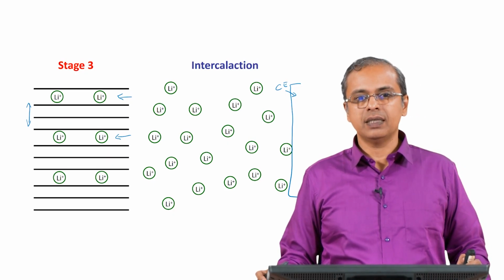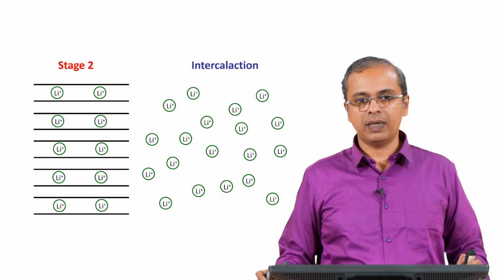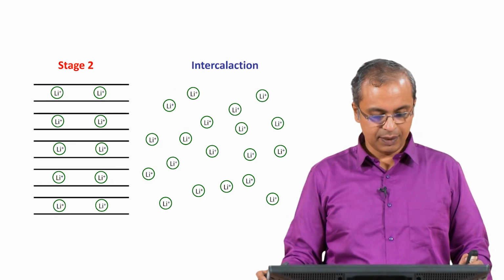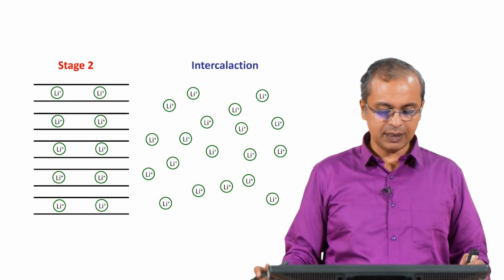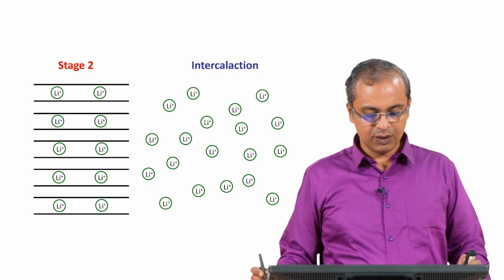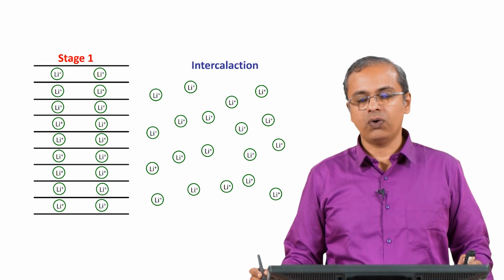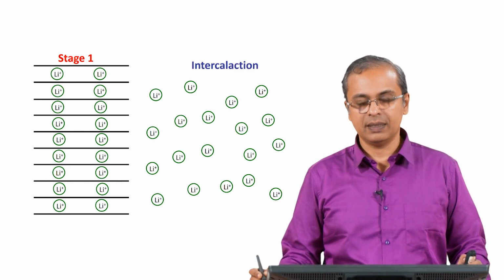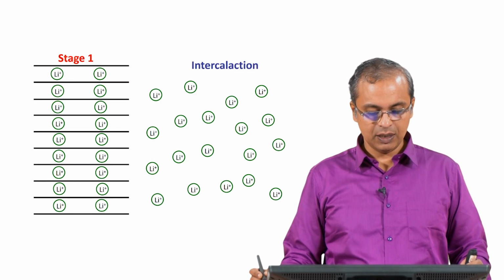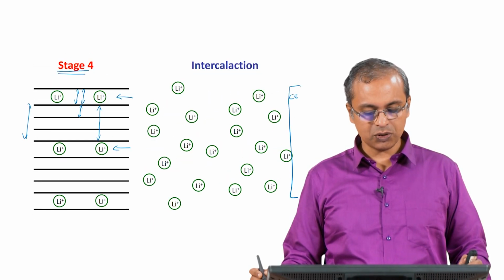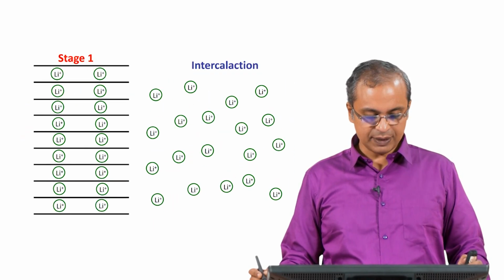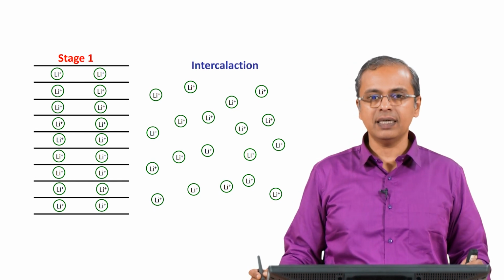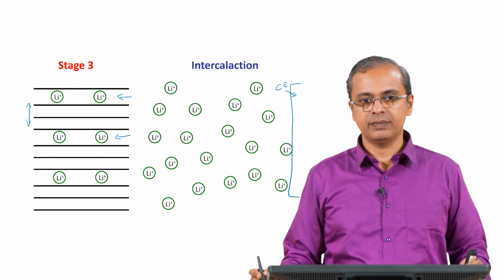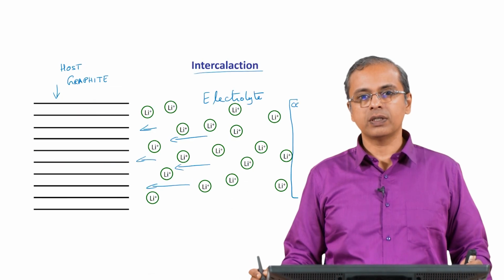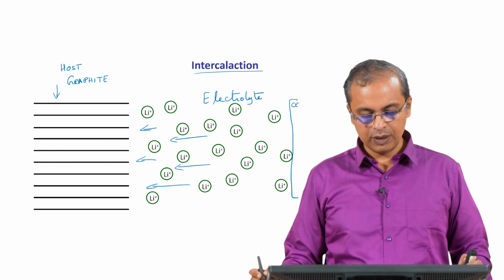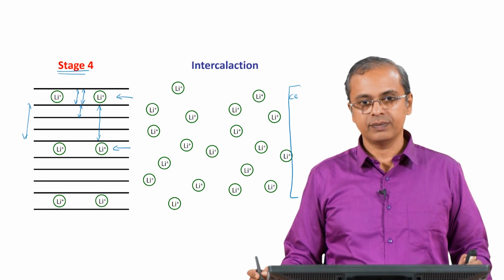We can continue this and you will have stage 2 where you have 2 layers of graphene between 2 adjacent lithium layers, and then you have stage 1 where you have all the graphene layers intercalated with lithium layers, lithium ions. So these are all the stages. So when you discharge also it will do the opposite. So if this is the charged condition and I start discharging the cell, it will go like this. Now all the lithium has gone to the counter electrode, you recharge it, it will do this.